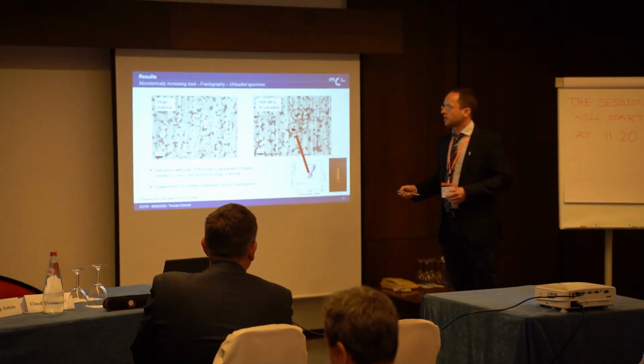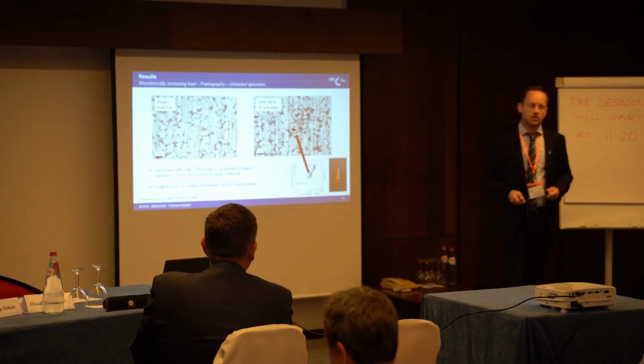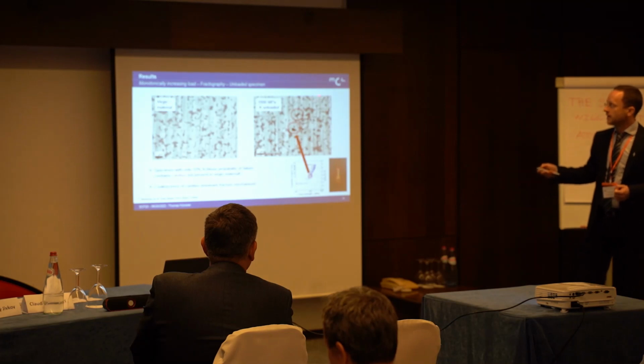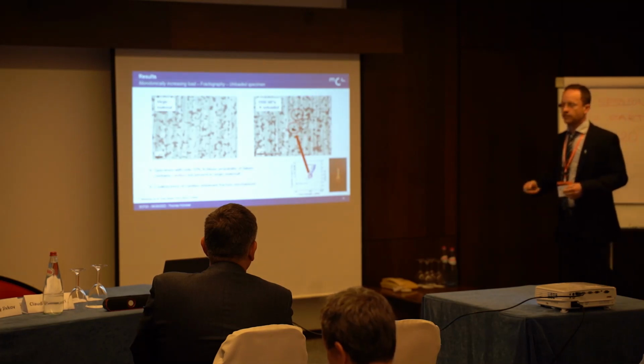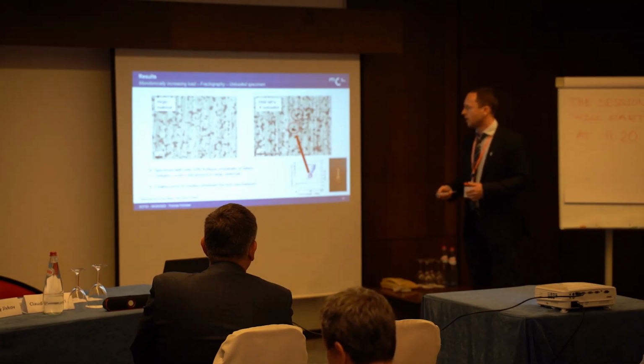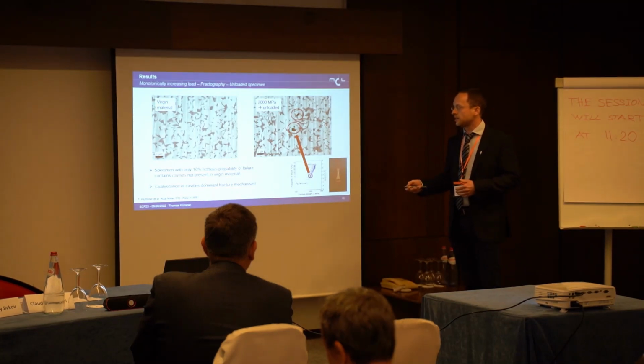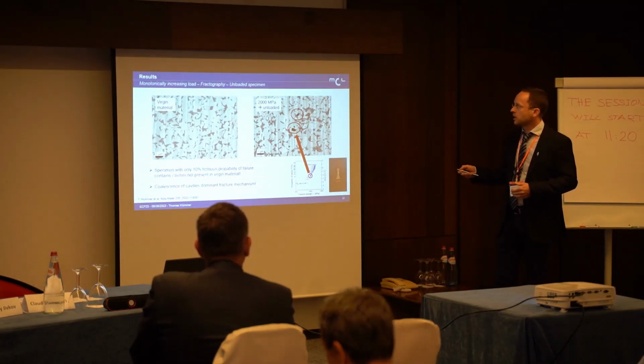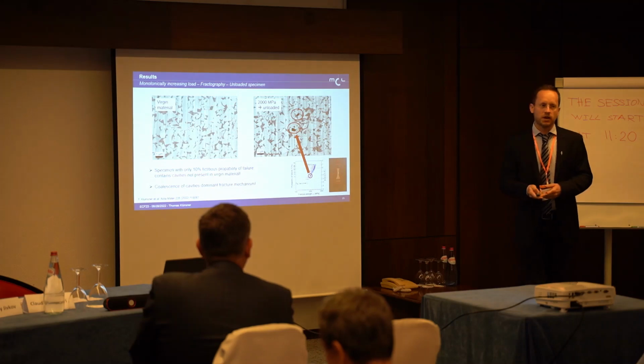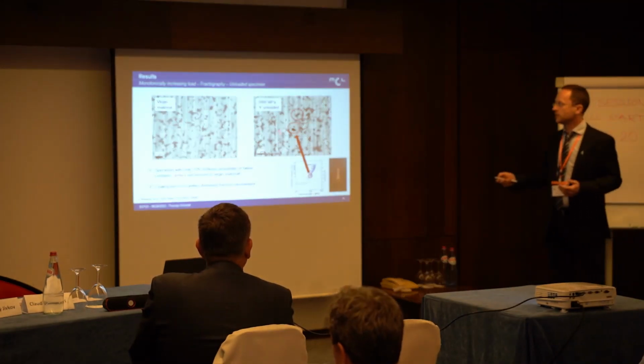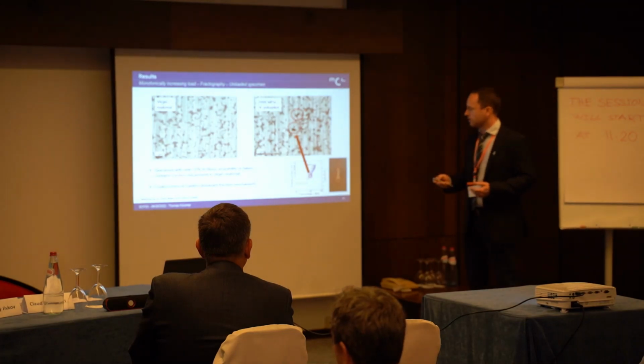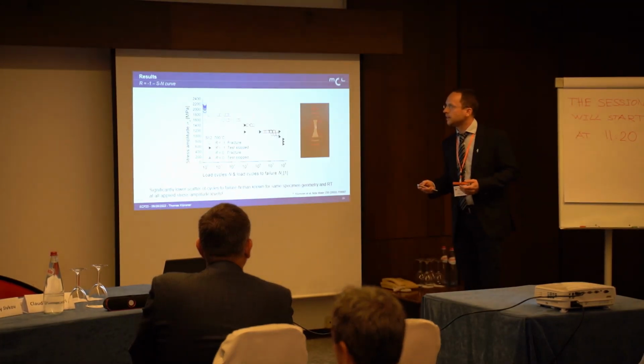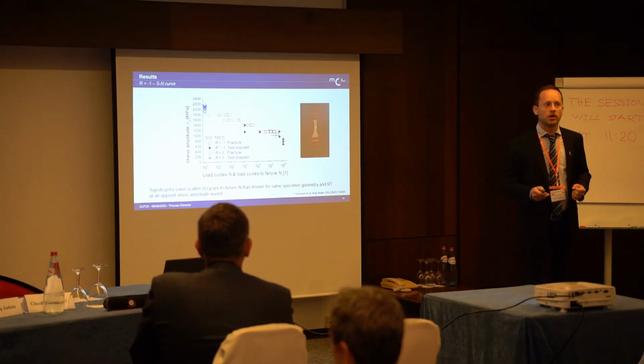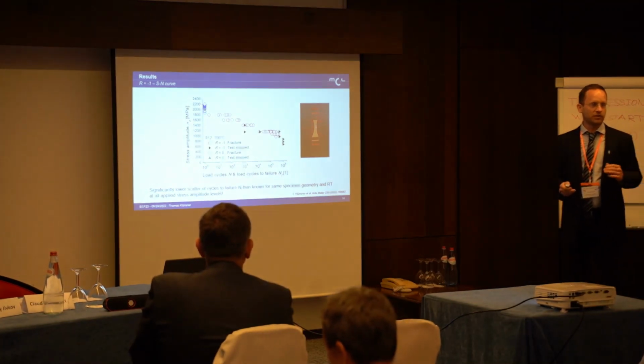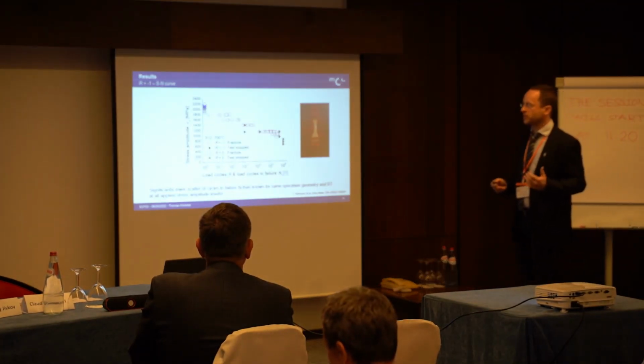The very reason, if you look at the virgin material, is, or I'm convinced of that, that you find defects that form in situ during loading, or cavities that then coalesce to become the dominant fracture mechanism under these kinds of loading conditions. So if temperature and stress are high enough, that happens. Under monotonically increasing load, and it's also the case under R=-1 loading, if the combination of temperature and stress amplitude is high enough or sufficient.